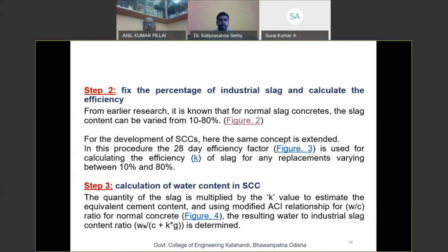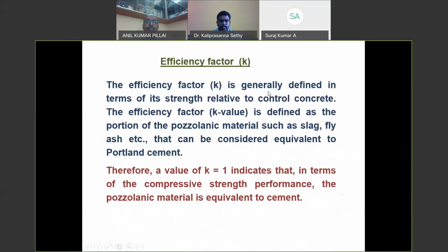Like in this procedure, the 28-day efficiency factor, so I'm talking about efficiency. The efficiency factor, that is nothing but the K value, is defined as the portion of the pozzolanic material. Pozzolanic material we are using here is slag. So it is defined as the portion of pozzolanic material like slag or fly ash, etc., that can be considered equivalent to the Portland cement. So if we have a value of K equal to 1, it indicates that in terms of compressive strength the pozzolanic material is equivalent to cement.